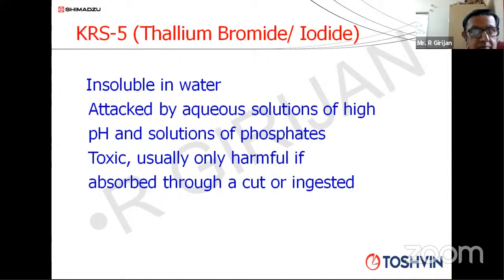And there is a very popular window material crystal called KRS5. It is nothing but a 1:1 mixture of thallium bromide and thallium iodide. It's a wonderful window material. It has got a wide range. It can go down to even 250 inverse centimeter, completely covering your mid-IR range, and it is insoluble in water. You should be careful only about two things. One is, you should not use very highly alkaline pH solutions, meaning anything with pH beyond 10 or 11. That can attack the material. And solutions of phosphates. These are the two things you should avoid with this material. Otherwise, it can be used for aqueous samples and non-aqueous samples. You can even wash it with water, nothing happens.